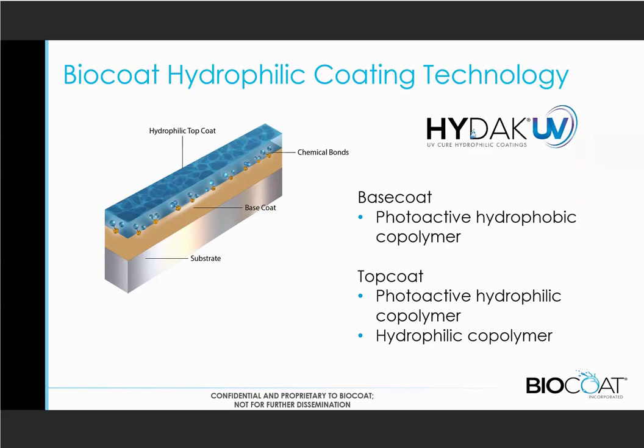So just to go a little bit into this hydrophilic coating technology for the HYDAK UV. Again, as I mentioned, this is a bilaminar system, and we went through it. We have a hydrophobic base coat that we apply that adheres very nicely to the substrate. What we've done is change out the thermal groups and copolymerize in some photoactive monomers, so that is now part of that base coat polymer. What these do is allow it to bond nicely to the substrate, cross-link to itself, and also be available to bond and grab onto that hydrophilic top coat.